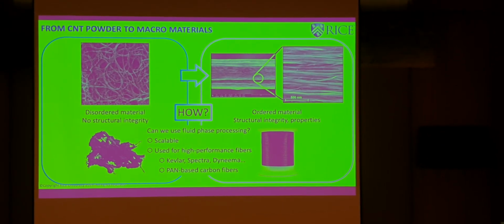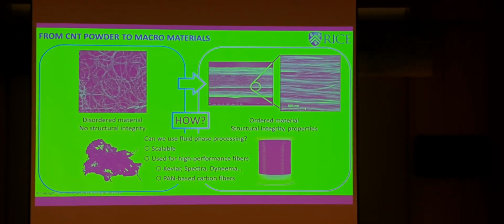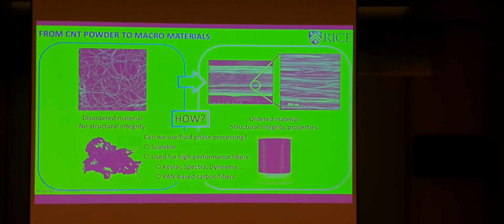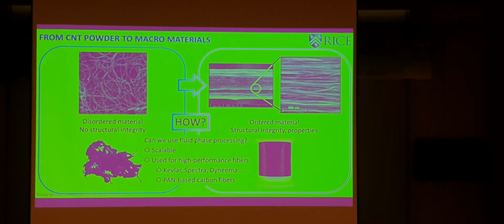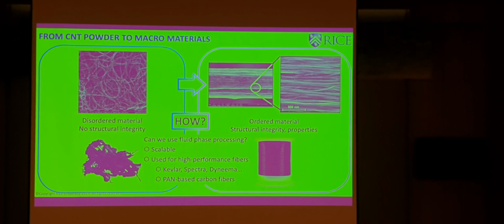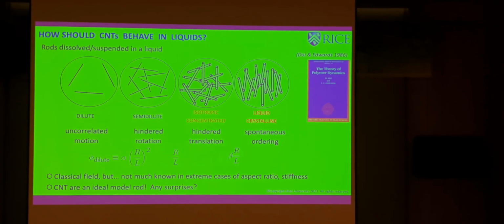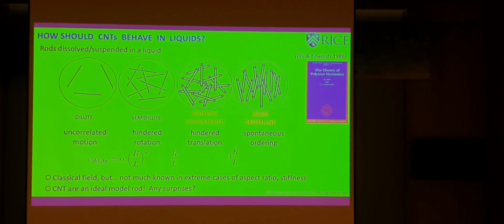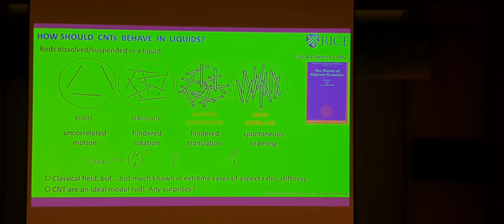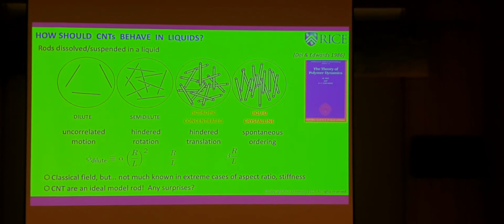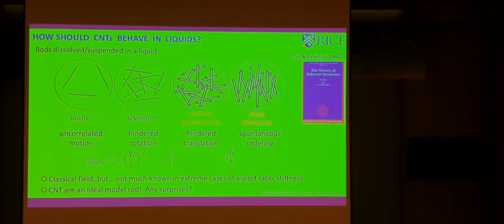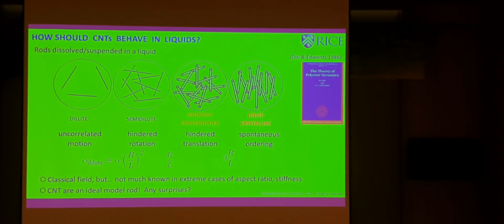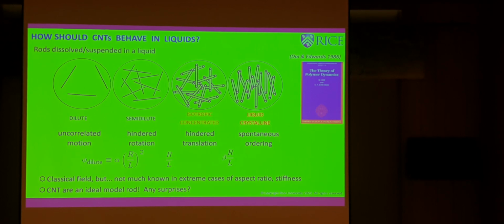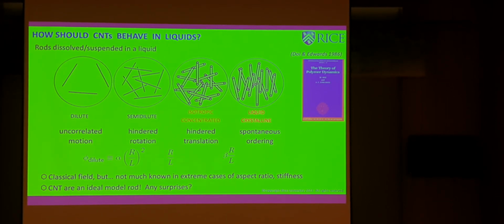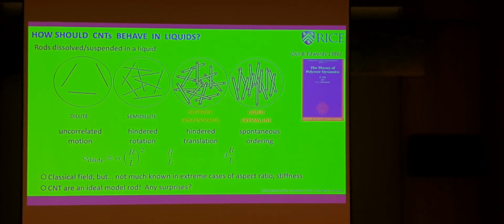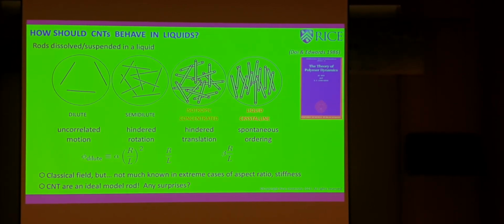Well, if you can use a fluid phase, you have a lot of advantages because it's scalable, but you also can use a technology platform that was already used for other materials like Kevlar, Spectra, Dyneema, PBO, and PAN-based carbon fibers, right? So what would you expect if you do that? Well, if you can get the nanotubes into a liquid, you would expect that they would behave roughly as rods. When they're dilute, they should act individually, and then progressively they should find themselves until at some point they would get so crowded that they could not exist in a disordered state in the liquid phase. And so they either would crash out of solution, or they would phase separate into a liquid crystal.